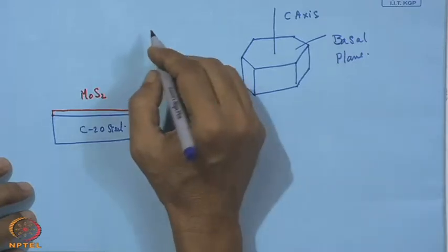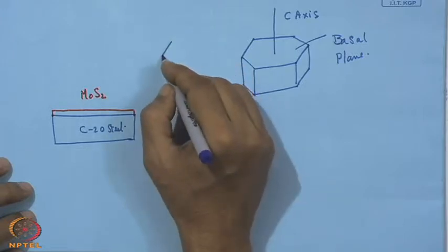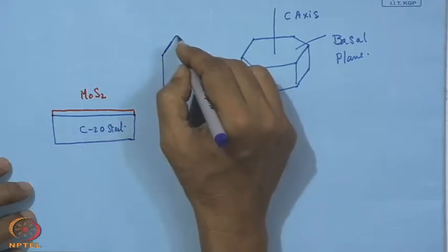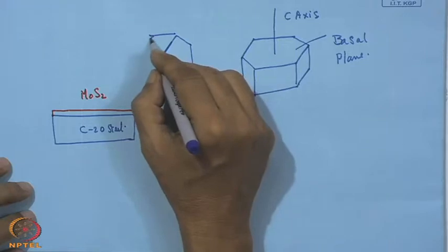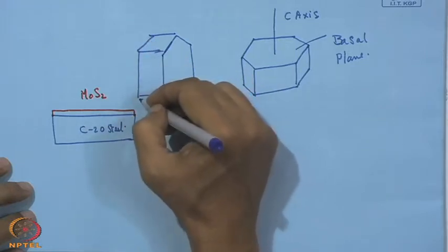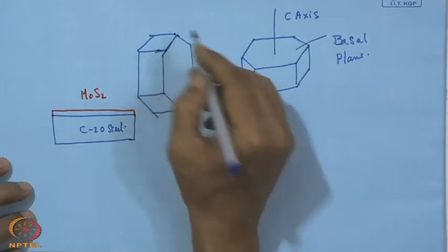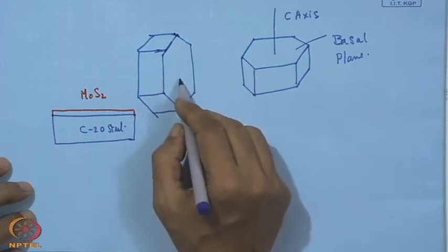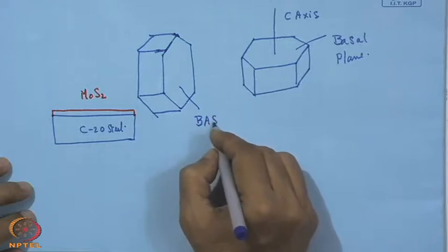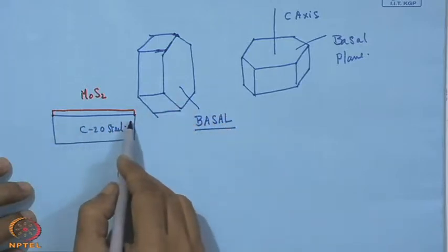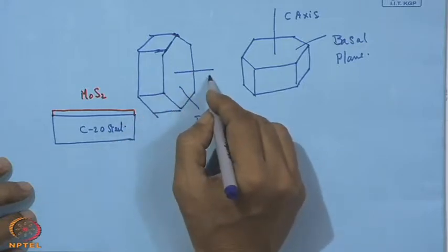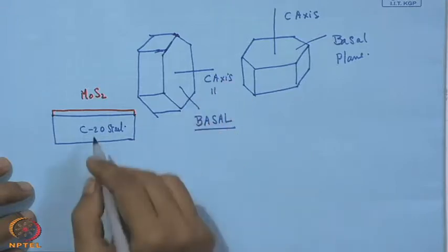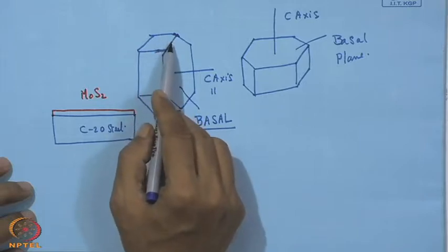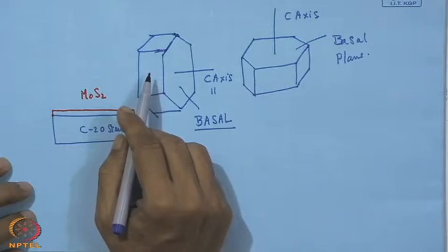another extremity. So, another extremity means this way. Let us have a quick look here, that this is another situation. Okay. So, here what we see, this basal plane, this plane, is no more parallel to the substrate surface, but it is perpendicular. That means the C axis is now parallel to the substrate surface, and this is actually the edge plane, and that is now parallel to the surface. So, this is one of the extreme worst situations, under which condition we can have a very poor performance of this coating.